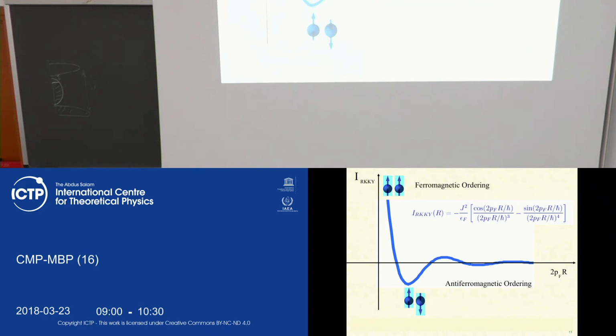What we see here is, first of all, at long distances, this is the three-dimensional case. The same oscillations exist in one dimension and in two dimensions. The tail of this function is 1 over r cubed, so it's a long-range interaction. The short-distance behavior, if you Taylor expand this function, produces 1 over r. And what is more important is that the function is oscillating and changes sign. Let's now assume that r is related to the lattice constant of your magnetic atoms. So for example, r is somewhere here. It means that the interaction between spins is antiferromagnetic. If, however, the lattice constant is in this domain, then the interaction between atoms is ferromagnetic, and so on and so forth. So this RKKY interaction can explain the mechanism of ferromagnetic or antiferromagnetic interaction mediated by conduction electrons.